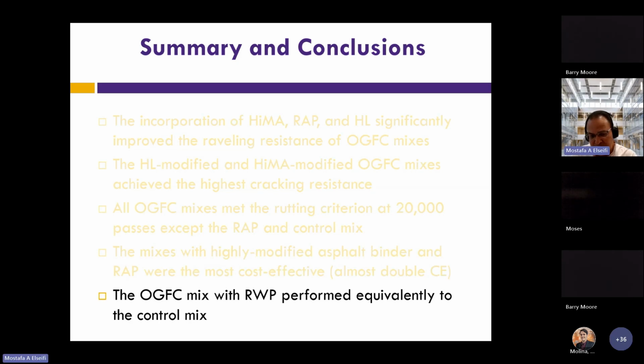And the mix with recycled waste plastic performed equivalently or slightly better than the control mix. So if that's something that is worth considering for environmental reasons, we found that the mix with recycled waste plastic performed slightly better than the control mix.